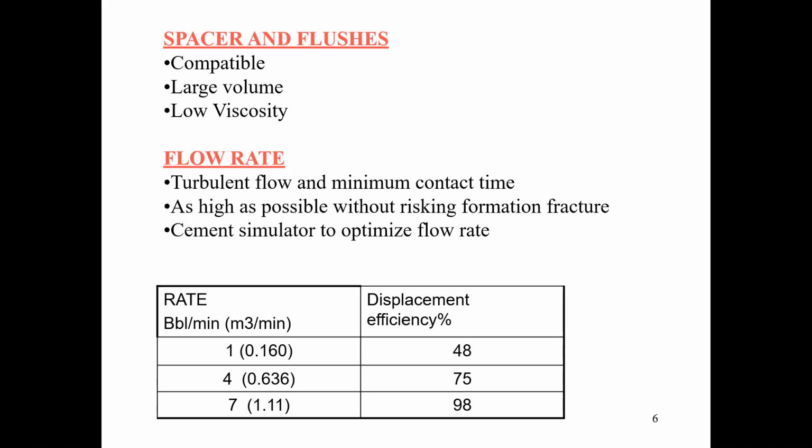I actually forgot to mention a few things. That is for hydrofrac areas. Nowadays we are also measuring mechanical properties of the cement. Young's modulus we measure. But why? Because the cement sheath is subjected to many stresses. In later instances, many times we are pressurizing and depressurizing the casing, so we are calculating for the tensile load also now. Poisson's ratio is also a mechanical property. The Poisson's ratio should be high, and your Young's modulus should be low for good cement.